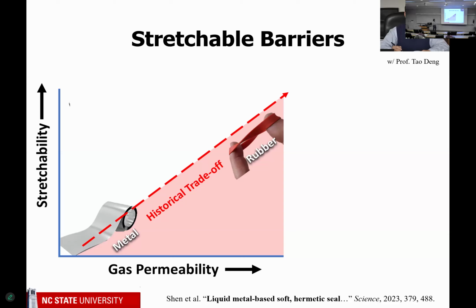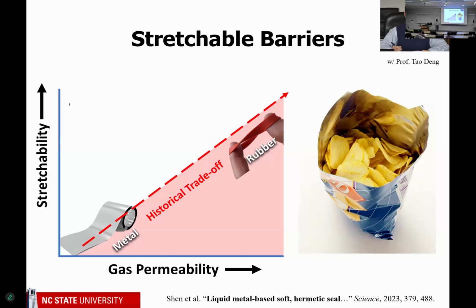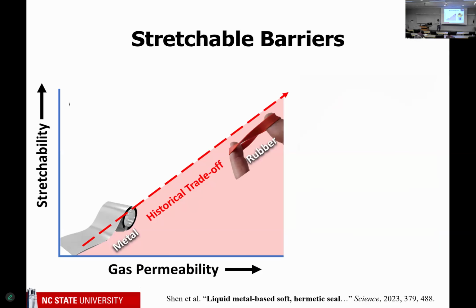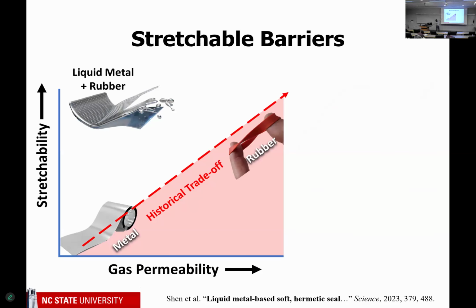And so if you don't believe me, even plastics, like the plastics that are used in bags of potato chips, tend to have a metal liner inside of them because otherwise the potato chips would go bad either due to moisture or oxygen getting in there. And so you can imagine how we kind of break this trade-off. We combined liquid metal with rubber to make a hermetic seal that has low gas permeability but is still stretchable and soft. Why would you do that?